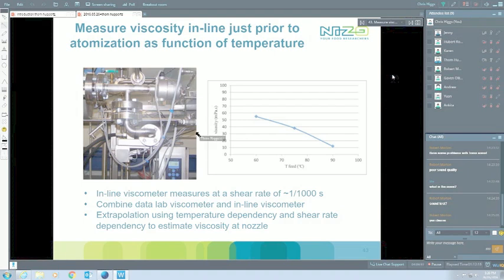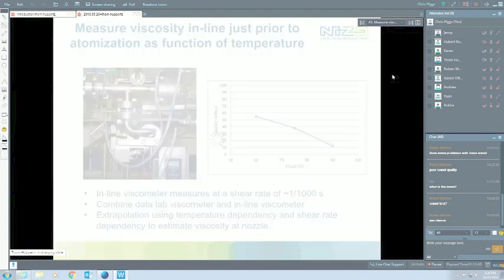But what we do have installed in the system is an inline viscometer, where we can actually measure the shear rate. It measures only at a single shear rate of about 1000 per second, but we can measure as a function of temperature. So combined with the data from the lab, we can extrapolate and see what it would be at a given condition when we're atomizing, and we assume a shear rate of maybe 100,000 per second.